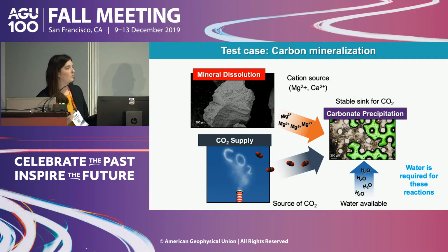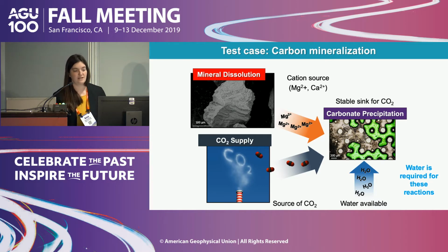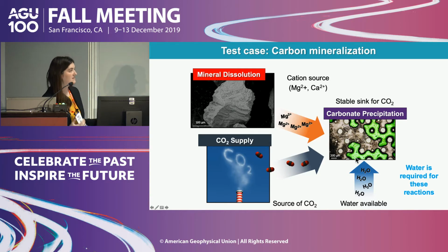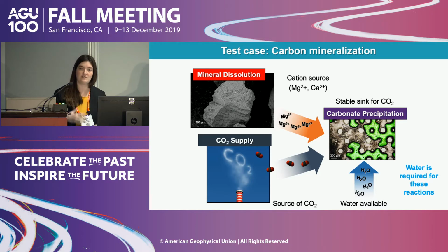Now, notably, water is required for all of these steps. It facilitates and enhances dissolution of minerals. The dissolution and hydration of CO2 is necessary to form carbonate minerals, and some of our carbonate minerals are actually incorporating water into their crystal structures. So we expect then that the availability and distribution of water is going to be a key control on the rates of these reactions and the degree to which they can progress.